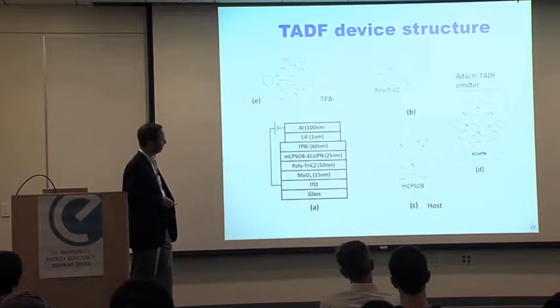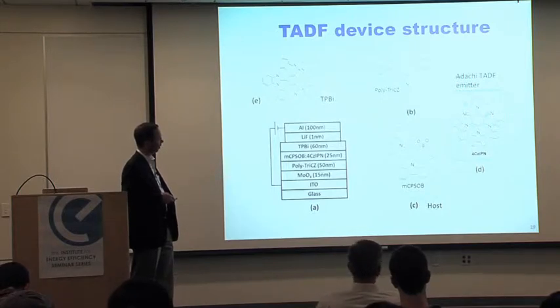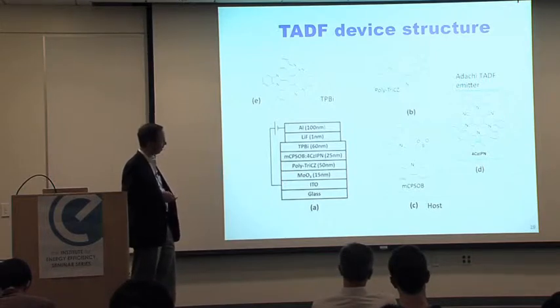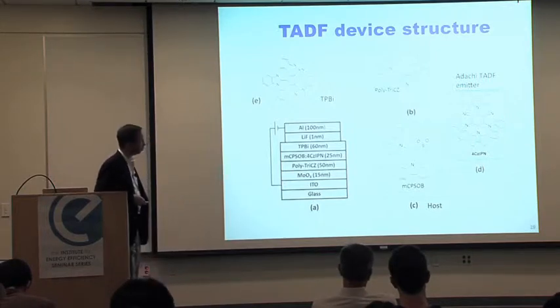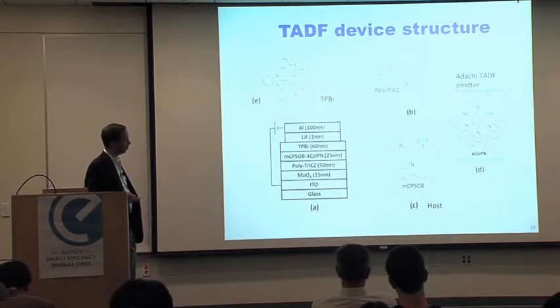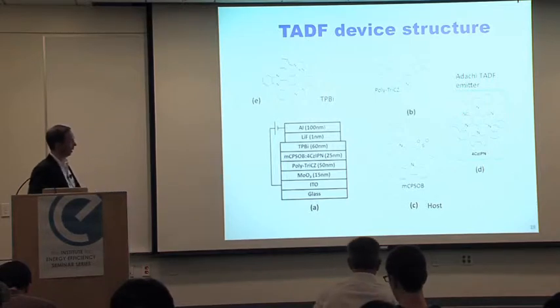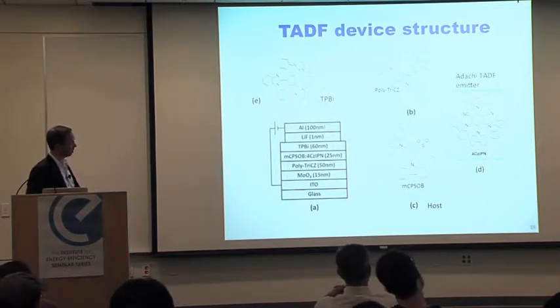And so on the right-hand side is the chemical structure of one of these TADF emitters. So you see the core here is a benzene, and then you have these 4 carbazole functionalities. Usually the HOMO, the highest occupied molecular orbitals, are located on one of these carbazole groups, and these cyano groups here, strong acceptors, that's where the LUMO orbitals are located. And compounds like this exhibit very strong thermally activated delayed fluorescence.